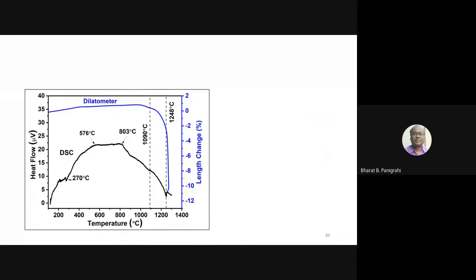If you overlap DSC and dilatometer, this is the DSC profile, and this is the dilatometer. Notice, you can see the events where you have a small melting and a large melting. You can see that when the melting starts, actually the shrinkage starts. So this tells us that this particular alloy is undergoing liquid phase sintering. The moment liquid is formed, the densification starts. So this proves that this particular alloy actually goes through liquid phase sintering.